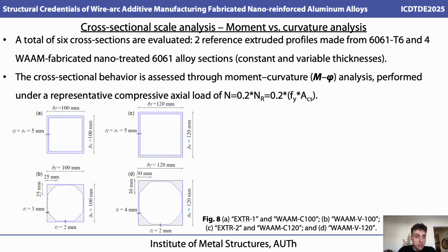In figure 4, we can see the examined cross-sections. You can see that the first set of 3 sections will feature an outer dimension of 100 millimeters, and the variable thickness section will also have 100 millimeter external dimensions, but they will have more material added at the corners where we have more stresses. And the last 3 sections will have 120 millimeter external dimensions, and they will again feature thickened corners.